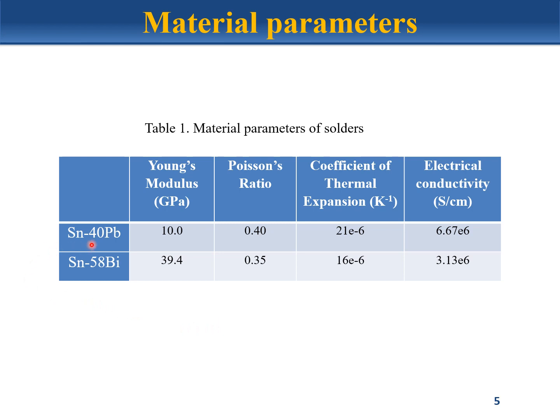As of right now, we have done research on lead-based solder, where there's 40% lead. And then the second one here is bismuth-based solder with 58% bismuth. We include the Young's modulus, the Poisson's ratio, coefficient of thermal expansion, and electrical conductivity. We do have other parameters, but these are the most important ones for the simulation.